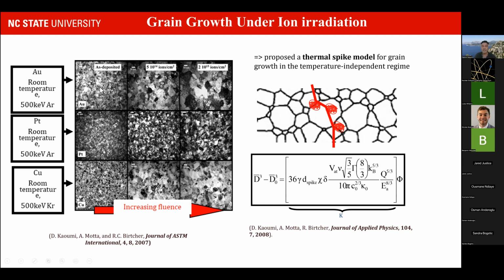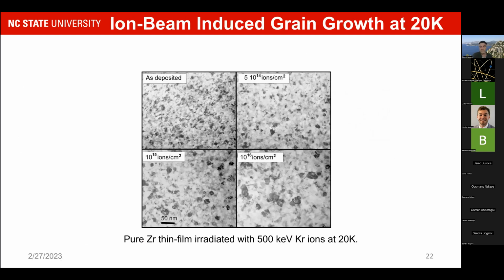What we observe is that regardless of the material, after irradiation, we see a gradual increase of the average grain size. And it doesn't matter the material, but also the type of ion, argon versus krypton, and the temperature. We did such experiments even at 20 Kelvin, where the diffusion processes are extremely limited. And we observe this type of grain growth under irradiation in zirconium, presented here. This eliminated the idea that the heat generated by the ion beam can be at the origin of this grain growth.